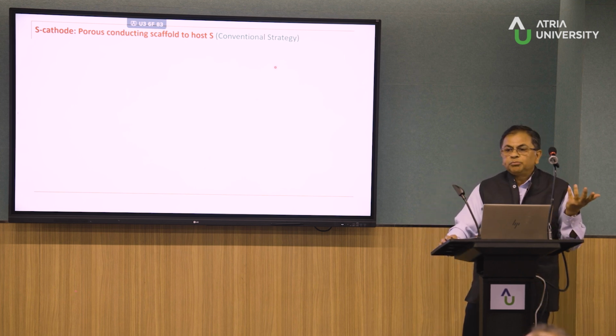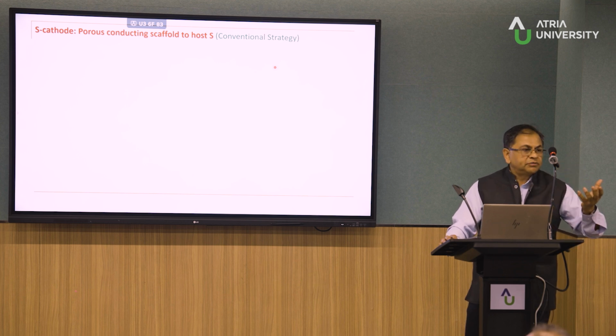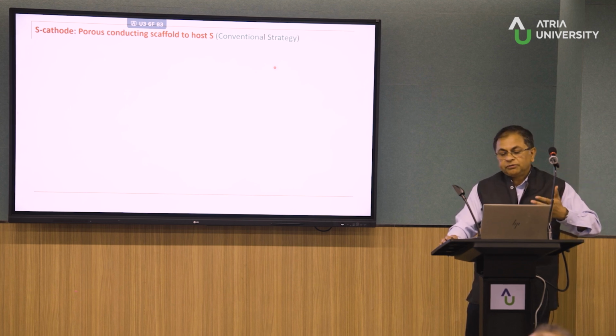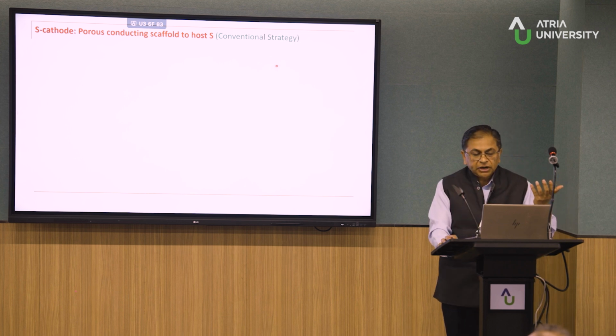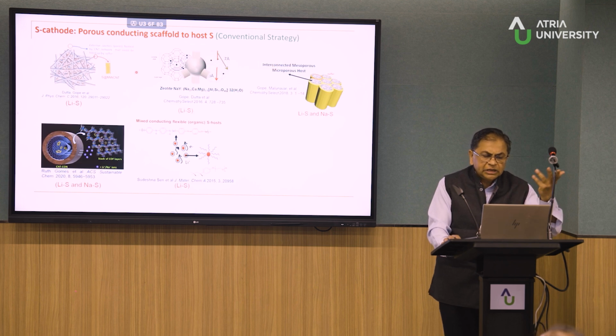Design very good porous hosts so that you can trap a lot of sulfur in it. And so, if you can trap about 70-80% sulfur in the matrix, then you can probably end up with a very high capacity battery. So these are some of the early examples.